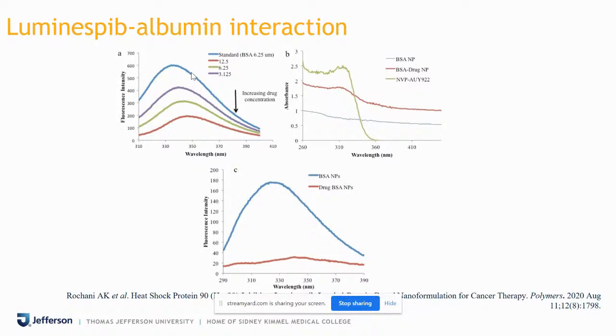So we thought that if the nanoparticle synthesis has been completed, the fluorescence would be extremely diminished. That was seen in figure C, where for the drug BSA nanoparticle, the fluorescence was around 20 units, whereas the native BSA nanoparticle, which doesn't have any drug, has a huge spectra, which can be seen in C. This was a confirmation that the drug is interacting with the BSA to form a nanoparticle.